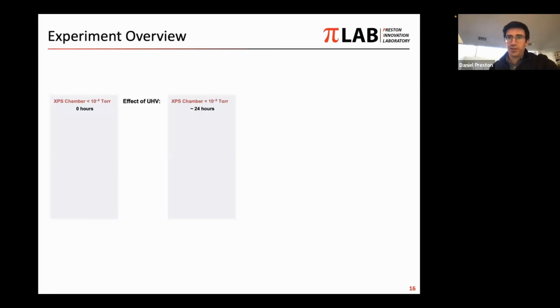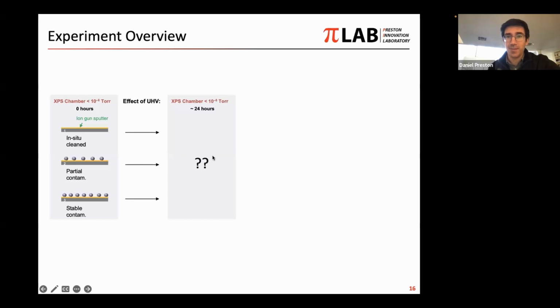So a quick overview of the experiments that we conducted to probe this area are shown here on the slide. We wanted to start in some ultra-high vacuum environment with samples that have different levels of contamination. Maybe a clean sample to see if it stays clean. Maybe some samples that are also already contaminated to see what happens to those as well. In this case, we used an XPS chamber for our ultra-high vacuum environment. And then we wanted to know what happens over time, right? So that's what the question mark is here.